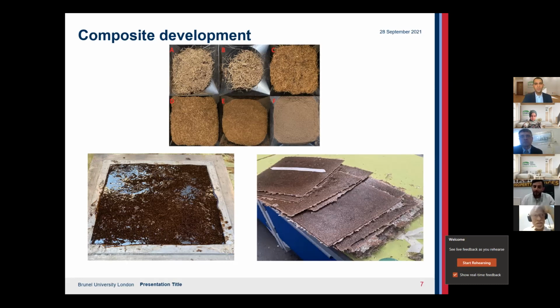The reason for me analyzing the sieve analysis is, one, in order to investigate the amount of each sieve within the unsieved. Two, in order to understand that each sieve fraction has a different density, and how the density will affect the composite when developing it based on a volume ratio or based on a weight ratio. Since the density of date palm fiber is low and the density of the thermoplastic or the polymeric matrix system is high, definitely the ratios will play a crucial role.